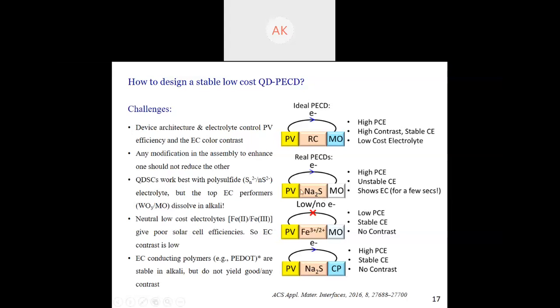Suppose we use an Na2S electrolyte, because we know that QDSCs work with polysulfide electrolyte, this Na2S will give very high power conversion efficiency. But the top electrochromic performers that we have, that is WO3, MoO3, or the transition metal oxides, are unstable in these alkalis. They tend to dissolve very easily. So the electrochromism, the color change, is seen for only a few seconds, and then the counter electrode is pretty much dissolved.